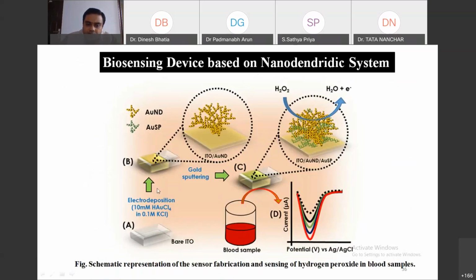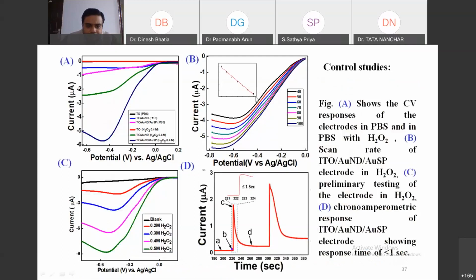It is the electrode, followed by the deposition of the nanostructure, then the sputtering of the nanostructure, and then electrochemical reduction of the whole process. And this is the signal output, right? This is the response of the hydrogen peroxide against various controls, and this is the response of the hydrogen peroxide with increasing scan rate. It is very much stable, and this is the initial response of the hydrogen peroxide at high concentration. This data is very much important.